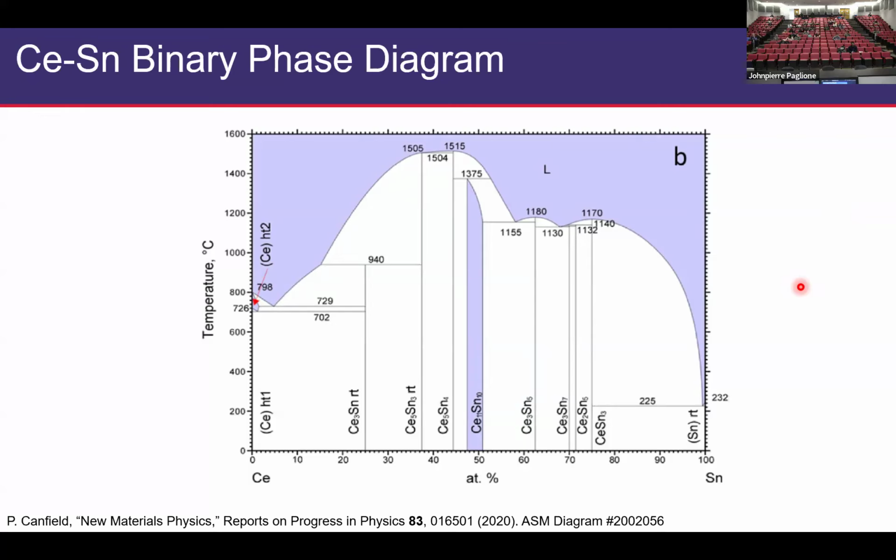So for instance, on this right side, you see my mouse? You have access to this whole liquidus line. So you could put 99% tin and try to get way down here in temperature, right? But then you have a very small range of growth. Or you can go way up here and start here and go really slowly and follow this, have this whole range of liquidus to fall down on and enable your growth very slowly. But that means you have to go quite high in temperature, 1200 degrees or higher to start. So somewhere in the middle, you just aim for that.